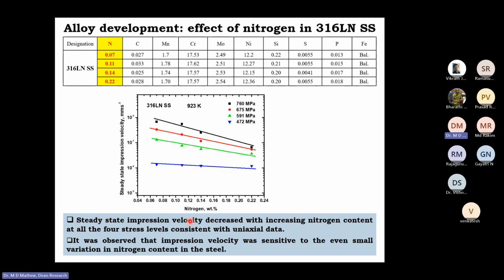So the steady state impression velocity decreased with increasing nitrogen content at all the four stress levels, and those results are consistent with the results from uniaxial tests. And it was also observed that the impression velocity was sensitive to even small variation in nitrogen content in the steel. Because if you see here, there were 4 different nitrogen levels, and the difference between each of these was not high.